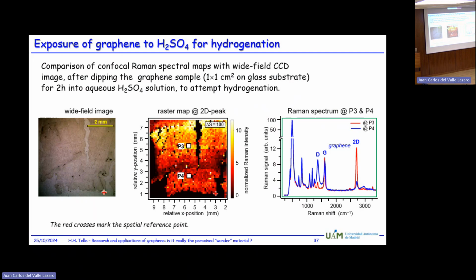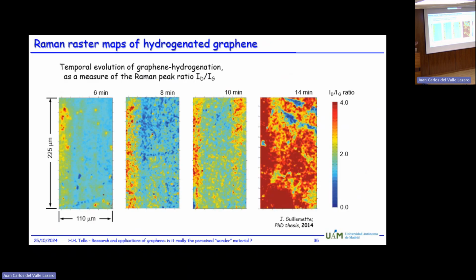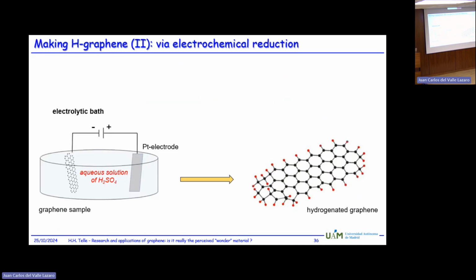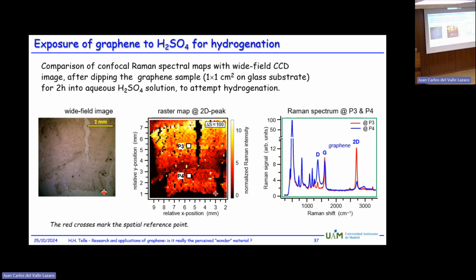And quite clearly, you can see the damage we introduced because there's no signal left. But you also see a difference between the top and the bottom, where the bottom was the part which was dipped into the electrolyte and the top not. However, if you know about electrolytes like that, you know that any aqueous sample has surface tension, so it creeps up your sample. So basically, what you see here, that you do not have a straight boundary, but you have a gradual transition. So here, there's more hydrogen attached than is at the top here.